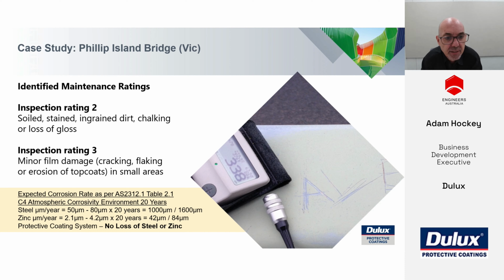Now, I pointed out that chart a little bit earlier in the AS 2312 table 2.1, that estimated loss of microns per year of bare steel or zinc coated steel. So this is just a bit of a chart to explain the amount of loss we would have had if that steelwork had no protection on it in this atmospheric corrosivity environment. So going by that chart, over the 20-year period, we would have had a loss of between 1,000 and 1,600 microns if it was bare steel. So 1 millimeter to 1.6 millimeter loss of steel would have occurred in that period if it wasn't protected.